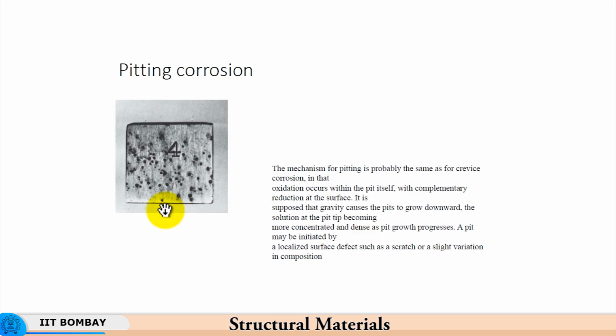So, we have seen that oxidation occurs in the pit itself with complementary reduction at the surface. It is supposed that gravity causes the pits to grow downwards, the solution at the pit tip becoming more concentrated and dense as the pit growth progresses. Actually, by gravity the corrosive liquid might continue entering the pit, and because of the pressure, the height of the liquid column is increasing. So, the surface which is to be eaten away will have a big amount of liquid column on top of it. So, some effect of increasing pressure on the fresh surface that is being corroded will also play a role,